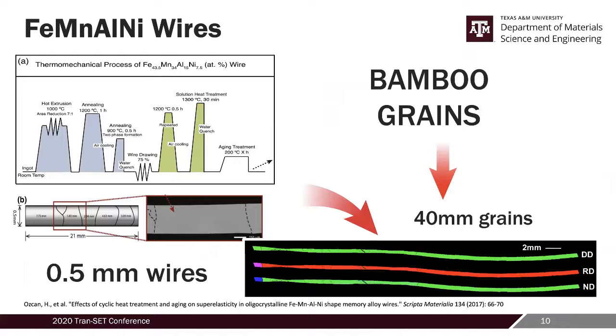So let's look at how wires work. If you want to make an iron-based SMA wire, this here is the processing technique that I showed in the left graph. We extruded our material, then we annealed it, and then we did wire drawing at room temperature. And this part here is where we induce the grain growth. We repeatedly heated up and cooled down the material from room temperature to 1200 degrees C. When you repeat this heat treatment a couple of times, you get grain growth.